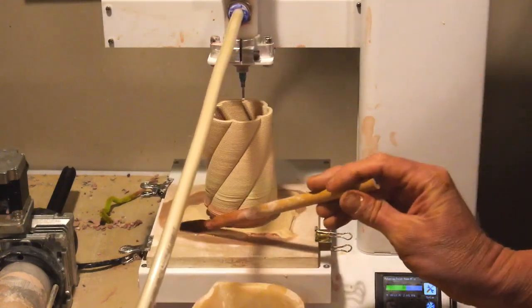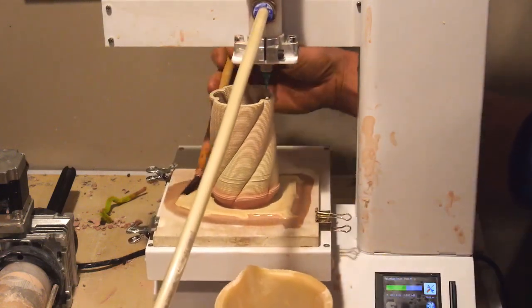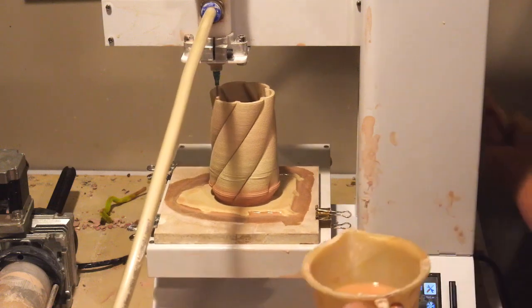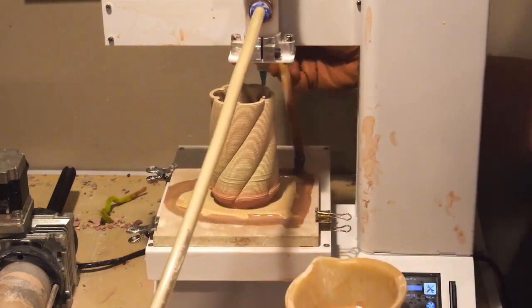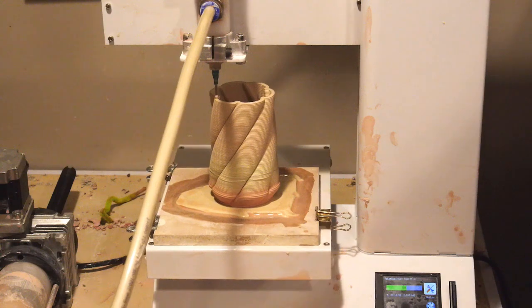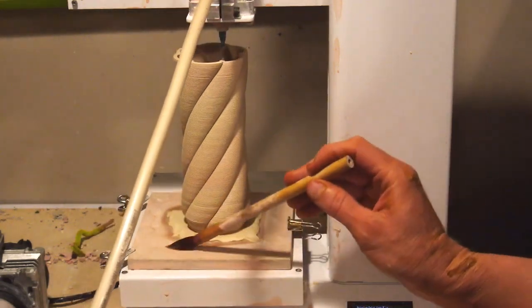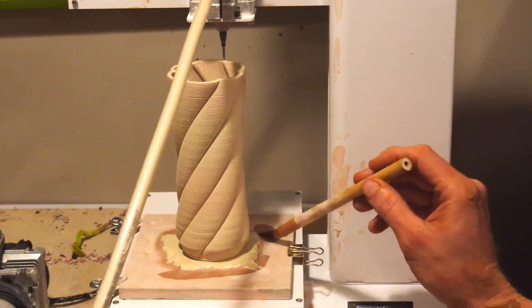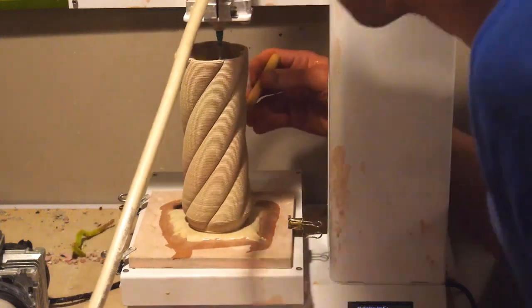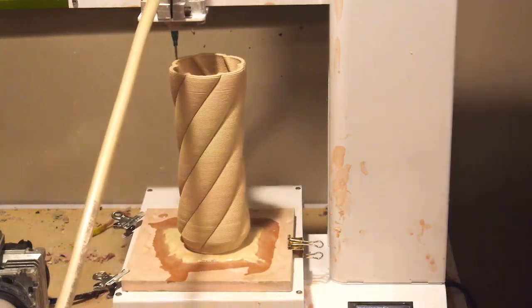Further on with the print, I come back once in a while to check in. I'm running this printer while I'm doing other tasks in my studio, making pots other ways. I print these twisted vases in the printer. I've got that blow dryer on a lower setting, because I don't want it to dry too fast — if it dries too fast, it can actually shrink the layers, and you'll notice a layer shrank compared to the others because the clay is so wet. So just a nice low cold setting to help dry the clay a little bit faster.